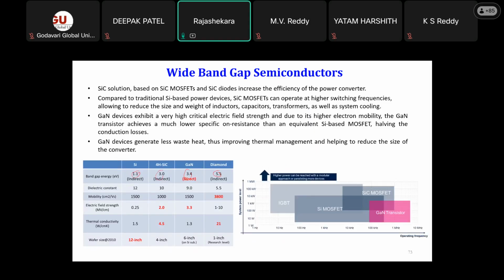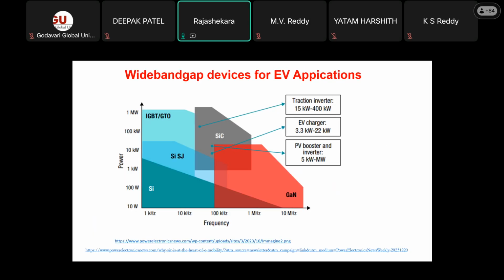And mobility. If you use IGBTs, you can switch up to 10 to 20, 50 kilohertz. With silicon MOSFETs, you can go up to 100 kilohertz. If you use silicon carbide, theoretically up to 1 megahertz, and with gallium nitride you can switch up to about 5 megahertz. So the trend is to go for higher switching frequencies. Gallium nitride is mostly available at 600 volts, but work is going on 1200 volt gallium nitride devices. Silicon carbide is available at higher voltages like 1700 volts or even higher, and can also go for high power inverters. For traction inverters, 15 kilowatt to 400 kilowatt, EV chargers 3.3 to 22 kilowatt, and boosters up to 5 kilowatt to 5 megawatts, you can use all these silicon carbide devices.